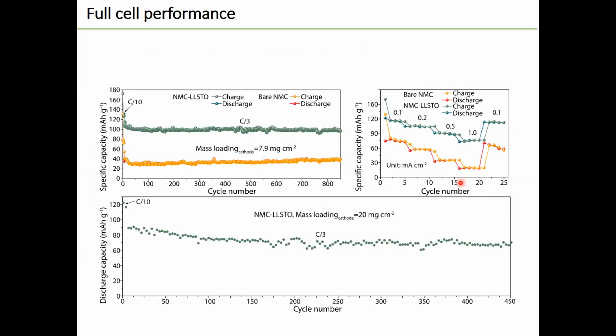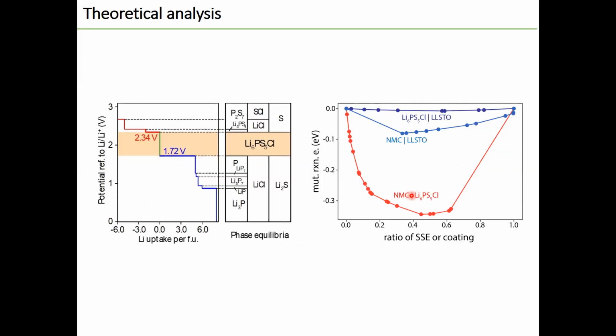After that, we tested the cycling performance at different mass loadings and the rate performance. It is obvious NMC with coating exhibits a higher capacity, stable cycling and better rate performance. After 850 cycles, the capacity still retained at around 100 milliamp hour per gram. When we further increase the mass loading to 20 milligrams per centimeter squared, the performance is still very stable. The good performance was contributed by the stabilized interface.